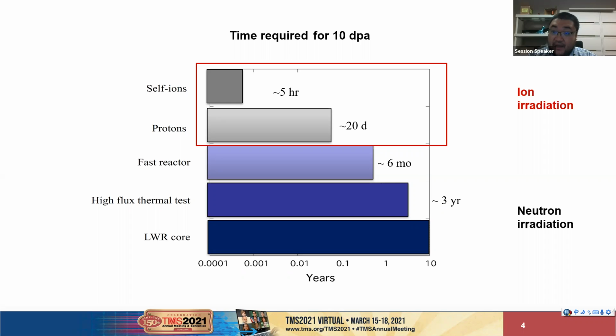Well, for the ion beam radiation, the time required is much shorter. For example, for the proton radiation, if you want to accumulate 10 dpa radiation damage, it's going to take only 20 days. And for the heavy ion radiation, which is much more impressive, the time required is only 5 hours. So as you can see, ion beam radiation has been used as a surrogate to investigate the radiation effect in materials for decades. Its advantages are pretty obvious: higher flux, higher fluence, and significantly reduced cost and time of the experiment.